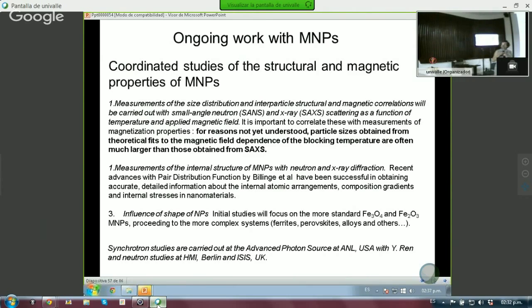And what we noticed is that if we do microscopic measurements, or we look with small angle X-ray or neutron scattering, there is a difference in the results between what we get from the microscopy and what you get from the neutron or X-ray measurements, because in this case you're taking a free sample without confining it on a grid. So what we started doing is small angle neutron scattering and small angle X-ray scattering, and then we were also interested in, the number 2 is measurements of the internal structure.